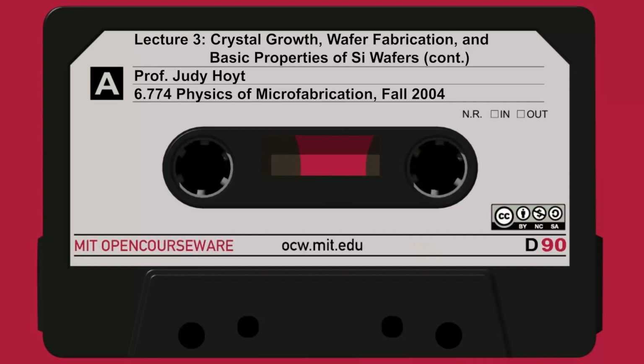If this is the energy band gap and the forbidden gap, so to speak, and those are the valence and conduction bands, a shallow donor is like arsenic. Remember, we had arsenic or phosphorus, and it's shallow because its energy level, it's a localized state also, but it's very close to the conduction band, say within a few tens of millivolts, 0.03 electron volts.